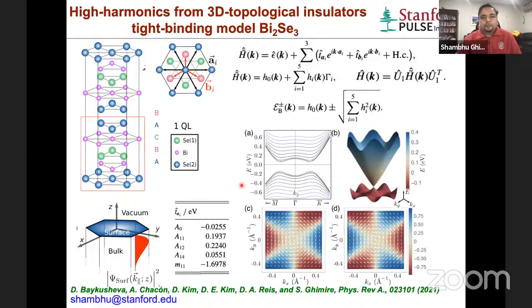So to understand the microscopic origin of the harmonics in these topological insulators, we resort to a tight binding model. We start with this Hamiltonian, and we produce this band structure for the bulk, and this is the surface mode. As you can see, a nice Dirac cone is formed by the valence and conduction bands on the surface. And these are the spin polarizations for the valence and conduction bands of the surface. As you expect, we have this spin-momentum locked configuration, which is the signature of topological insulators.